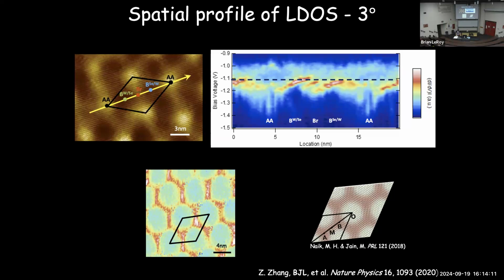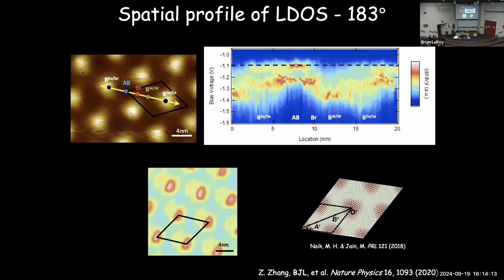Doing the exact same measurement with the 183-degree twist angle, the same physics is happening. You have this twist angle, you get these flat bands, you get states living along the unit cells here right near the edge of the valence band.